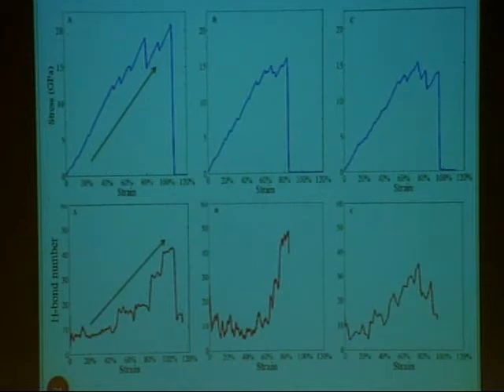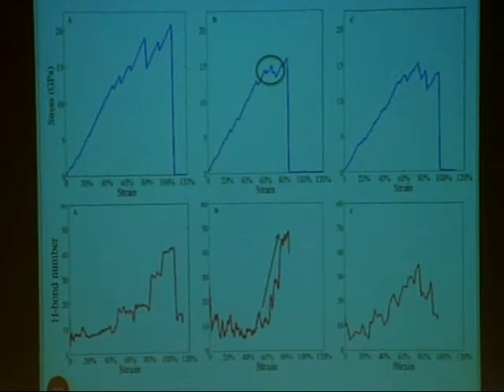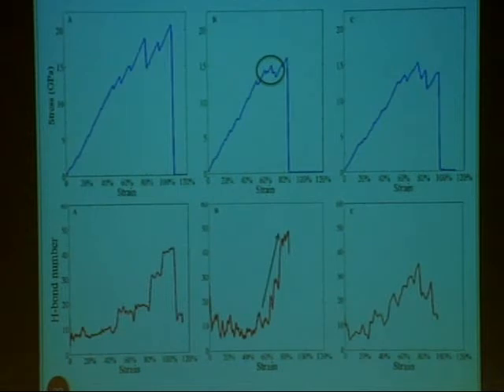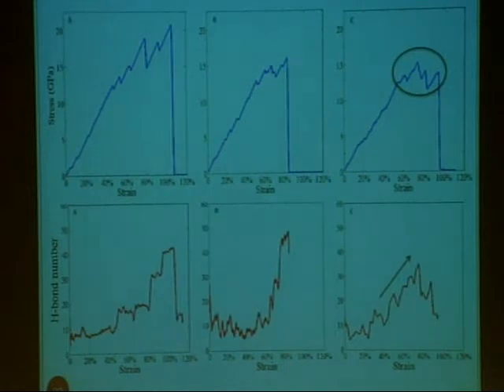This model has the highest strength as well as stiffness. For the next model, during the necking range, there is a high amount of hydrogen bonds that form, which makes sense — a high number of hydrogen bonds break in the collagen, meaning it will have higher accessibility to form hydrogen bonds with the surface of the hydroxyapatite. For the last model of 21 angstrom thickness, we showed a quite gradual increase in hydrogen bonds. This area is a combination between creeping and necking, which causes the gradual increase, because during creeping the same amount of hydrogen bonds remains within the collagen and at the collagen-hydroxyapatite interface.